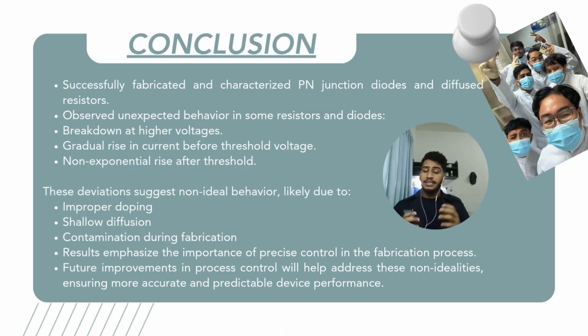In conclusion, we successfully fabricated and characterized p-n junction diodes and diffused resistors. Through the characterization of the IV curves, we observed that while the resistors generally followed the expected behavior, we encountered unexpected results such as breakdown at high voltages, a gradual rise in current before the threshold was reached, and a gradual rise in current as opposed to an exponential rise after the threshold, and so forth. This deviation suggests that some of the resistors and diodes exhibit non-ideal behavior, likely due to fabrication issues such as improper doping, shallow diffusion, or contamination during the manufacturing process.